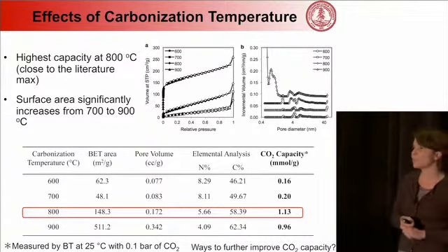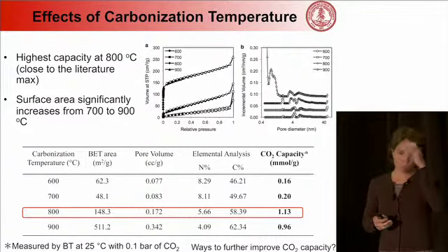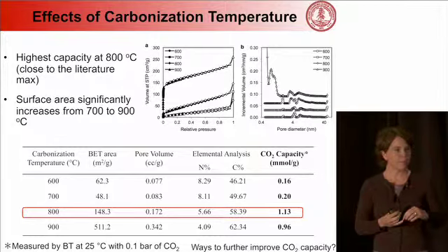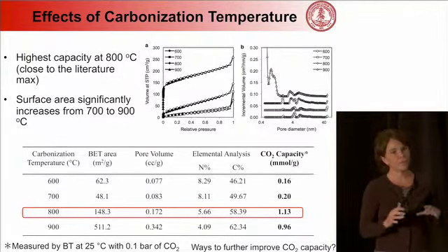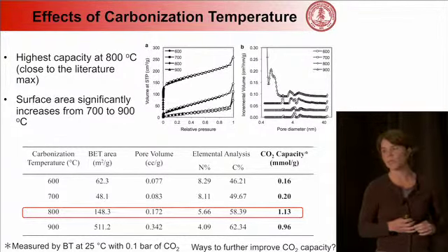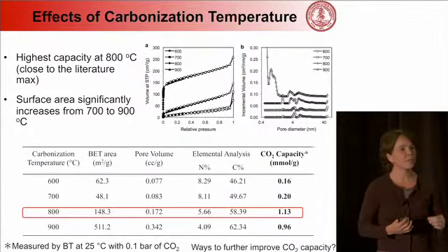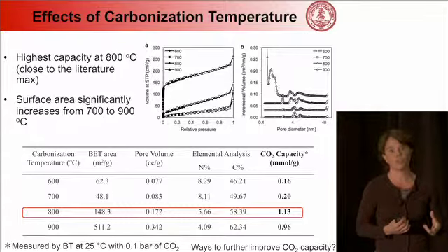So it gives you an idea of the pore size distribution. One of the things I want to mention here is that these substrates have some nitrogen functionality, which will hopefully enhance the uptake, which is what we see. But another driving force, not just the surface chemistry of these materials, is a thermodynamic driving force.